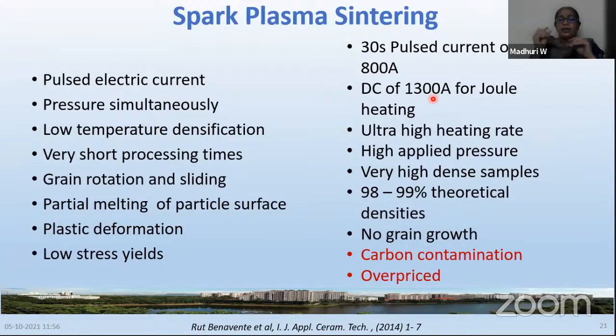Fine. And in a very short interval of time, you can quickly densify and crystallize your materials. And you will get very good high density samples, very close to the theoretical densities. Almost 99% of the theoretical density can be obtained.